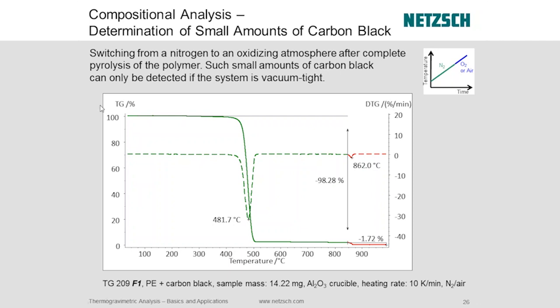Okay. So here what you see with this polyethylene sample is we heat it up to 1,000 degrees. We're going to do the first part under nitrogen. Okay, so we're going to get a pyrolysis of the polyethylene. So you see the weight loss, just a big weight loss step as we break down the polymer backbone. This is your derivative again, so you can see a really nice clean step. Maximum points around 482 degrees.